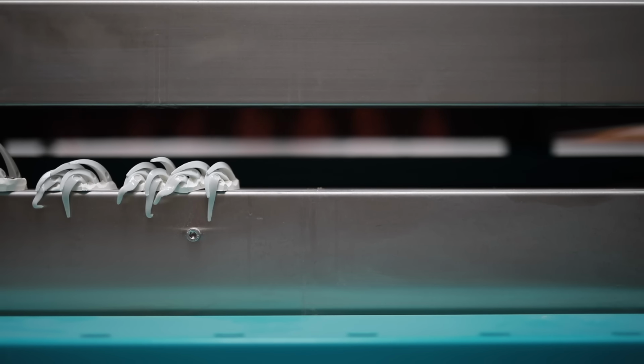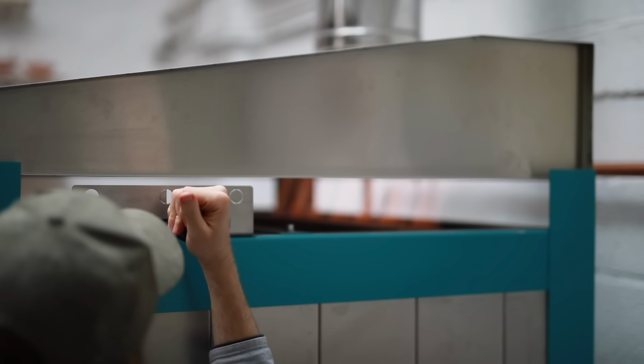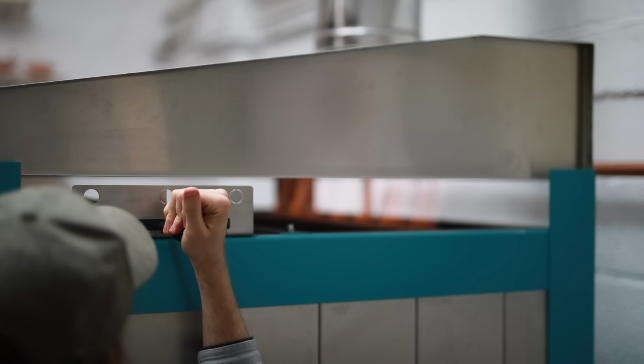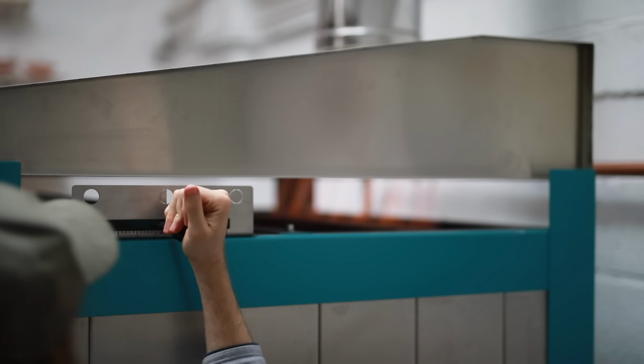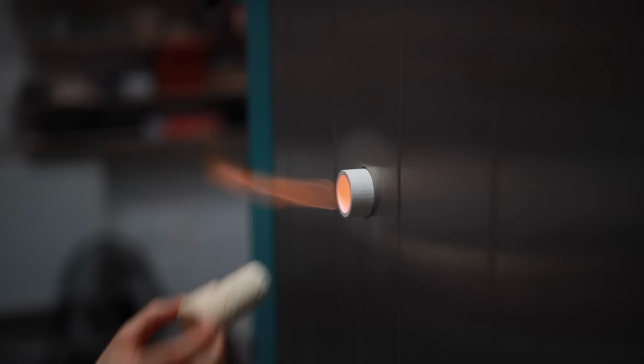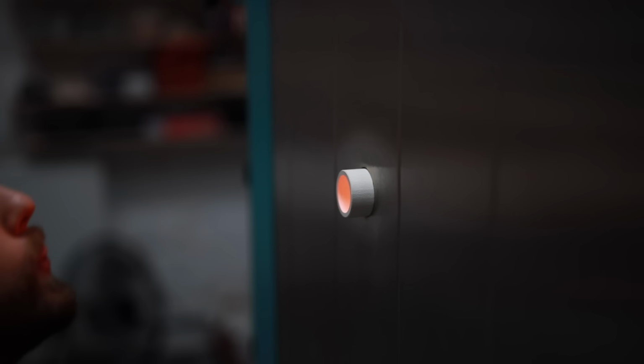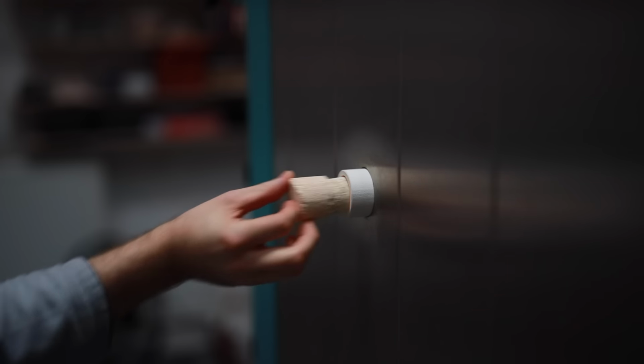As the reduction atmosphere takes hold, the fuel inside the kiln starts to burn less and less efficiently, and it starts to seek oxygen to attempt to burn more efficiently, as there's a severe lack of it inside. This is why the flames start to come out of the kiln, as they're seeking oxygen to burn with. And the fuel, which in this case is natural gas from a main supply, to burn efficiently, goes inside the clay and glazes and strips away an oxygen molecule which bubbles out, bringing iron with it, which is what's responsible for the large iron dots that can be found on my work sometimes.